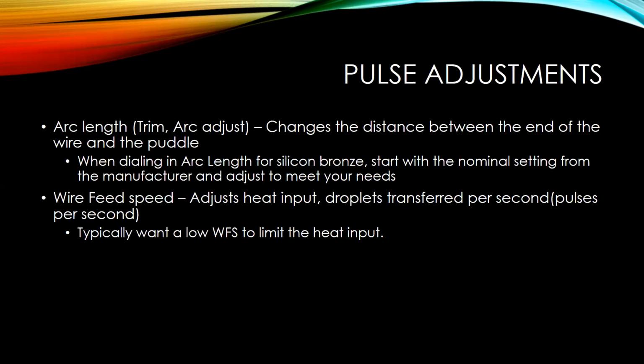So pulse adjustments. Like I had said before, arc length or trim or arc adjust is going to change the distance between the end of the wire and the puddle. Typically what I recommend is start out with the nominal setting for that when you are dialing in for silicon bronze, and then adjust as necessary, because for each joint type, you might have to adjust that a little bit depending on what you like. As far as wire feed speed goes, it'll adjust your heat input and your droplets transferred per second, or pulses per second. And typically you'll see running pulse on sheet metal with silicon bronze, it'll be on the low end of the machine, so low wire feed speed to limit that heat input.